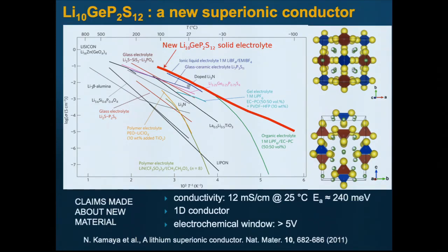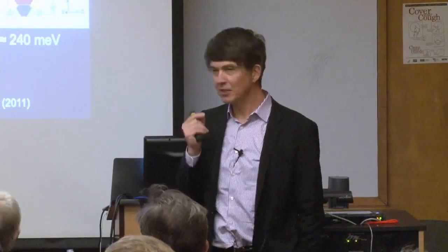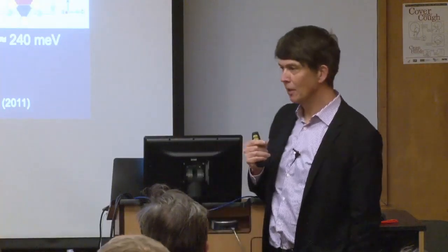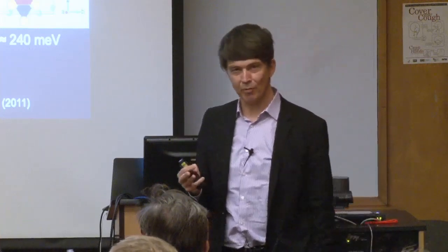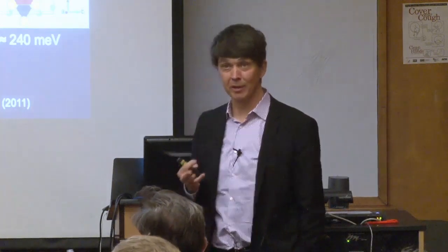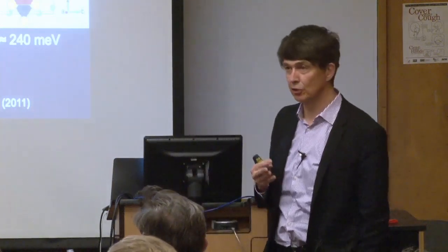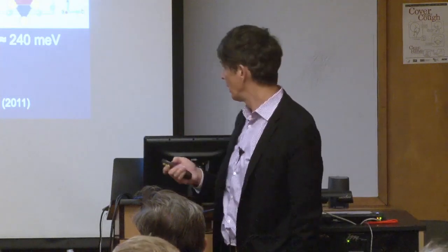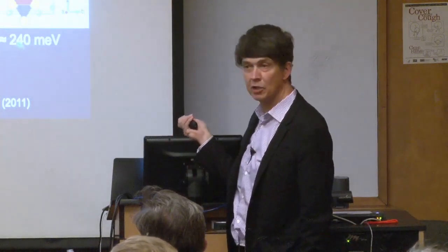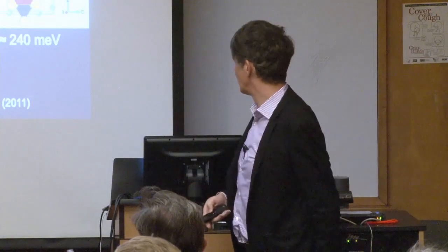The interesting thing about this paper is that it's almost completely wrong, except for the important thing, the conductivity. Almost everything in this paper has been proven wrong, but fortunately, the material indeed has super high conductivity, and it's sort of remarkable, right? It's a remarkably low activation energy for motion of ions through a solid.